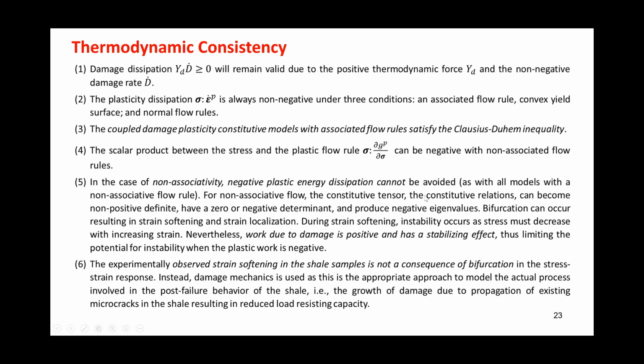non-associative law is that we have constitutive relations that are non-positive definite. It's not positive definite. In fact, it's non-symmetrical because of the non-associative flow rule. Therefore, it can have a zero or negative determinant and can produce negative eigenvalues. As a result, we can have bifurcation in the stress strain curve, and results in strain softening and strain localization.